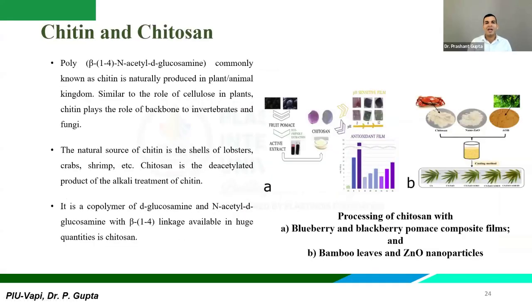Then this is chitin and chitosan. The first image, the A image, tells you about the fruit pomace, which is blueberry and blackberry. Pomace is nothing but the leftover waste after extracting the juice. From there, active extract is taken and converted into chitosan, and there is a pH sensitive film which is also rich in antioxidants. You might know berries are very rich in antioxidants, like people say eat berries, strawberry, blueberry, whatever berries you can eat. So the film will be very rich in antioxidants and it will create a pH sensitive film as well.